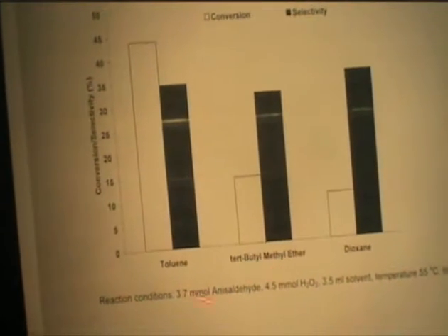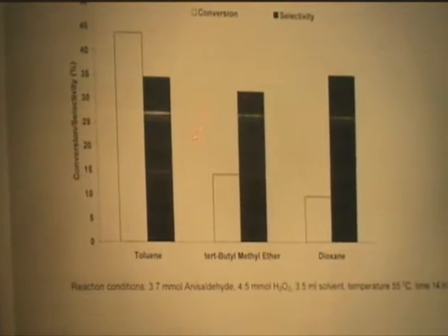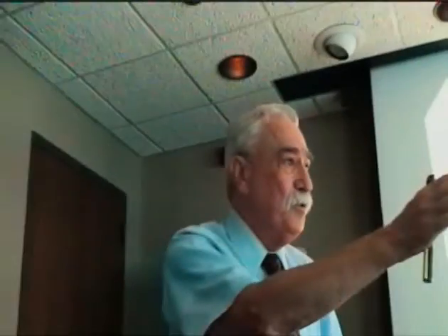And we compared the same sample with tertiary butyl methyl ether and dioxane. The conversions were about the same in terms of selectivity, in percentage. But you see that the conversion was much lower in the other solvents. So it is solvent dependent. Well, we think if the solvent is able to swell the pores, because they're not connected, right? House of cards, you can swell them. Then maybe the reaction is just going on around the edges of those little spheres. All it has to do is go in and come out.